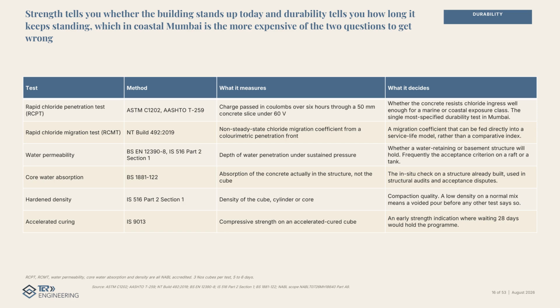Durability tells you how long it keeps standing. And in coastal Mumbai, that is the more expensive question to get wrong. The rapid chloride penetration test under ASTM C1202 is the most specified durability test in this city, and it is on our accredited scope. So is the rapid chloride migration test under NT Build 492, which gives you a coefficient you can put into a service life model rather than a comparative index.